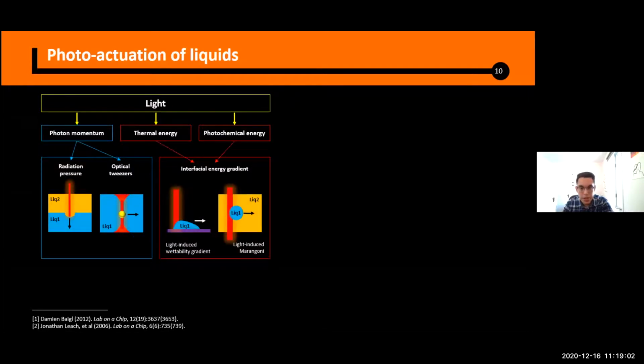The other 2 strategies are based on light-induced capillary forces to manipulate fluids. One of them is through the generation of a wettability gradient by partially illuminating a substrate with photosensitive wettability properties. So here we're changing the contact angle between the liquid and the surface, while the other one is through the Marangoni effect, where a gradient of interfacial tension along an interface between 2 fluids generates an interfacial flow in the direction of the gradient, that is, from the lower to the higher interfacial tension.